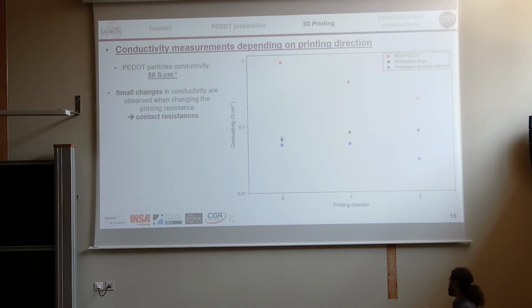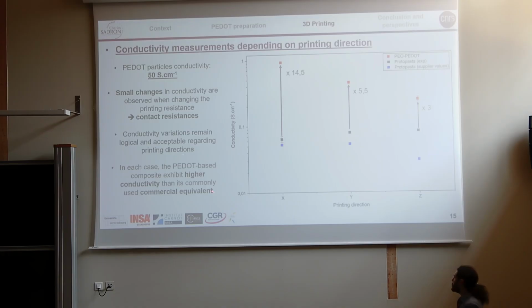And for our composite, you see that compared to the Protopasta, we have a small reduction of the conductivity when going from the X to the Y and the Z direction, which is something that's very well documented in the literature and is due to the contact resistances between the layers while printing the material. So this decrease is acceptable and remains logical. But also you can see that in each case, our composite exhibits higher conductivity than the Protopasta, which is well established, for example, in the DIY community.